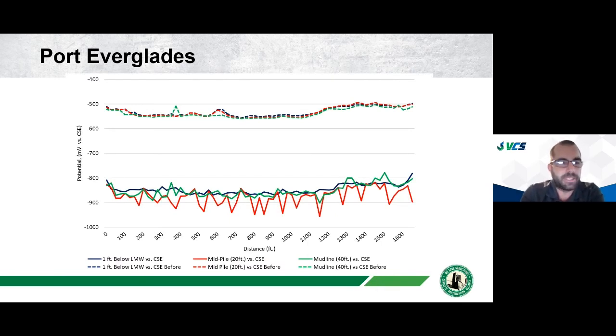Here you can see we measured the potential before installation of the CP system, and then we measured the potential after the CP system. And this drop ensures that it's working properly. So we're doing QA/QC to verify that the CP system's working properly.